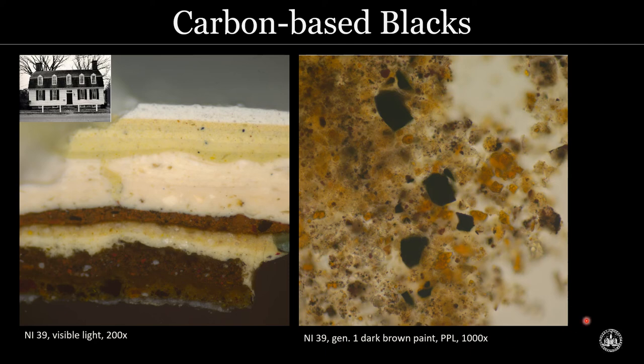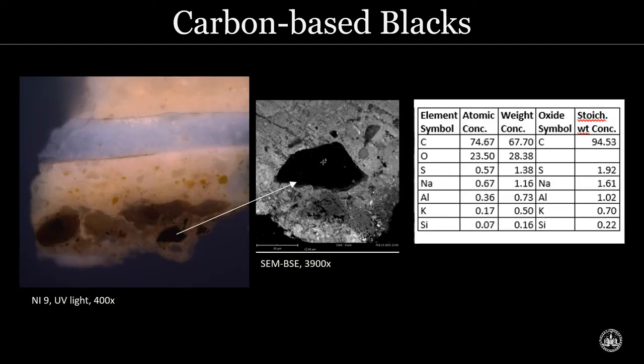And then here in the dispersion, we can see them even more closely. Some measured as much as 30 microns across, so extremely coarse. This brown paint also contained red and yellow iron oxides, as well as red lead pigment. So I did analyze these black particles. I was quite sure through microscopy that they were carbon-based blacks, but I wanted to be certain because they were some of the largest carbon-based blacks I'd ever seen.